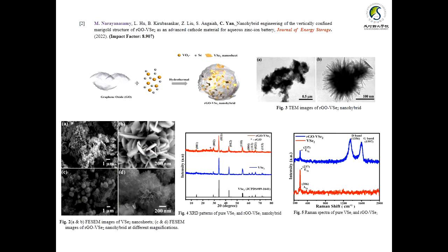We will be discussing the hybrid engineering of vertically confined marigold structure of RGO at vanadium diselenide as a cathode material for zinc ion battery. Here what we have done is, first we prepare the reduced graphene oxide and then add the precursor for vanadium and selenide source. Later on the graphene oxide acted as a template and wrapped VSe2 on top of it, vertically aligned together, and formed a novel marigold-like structure.